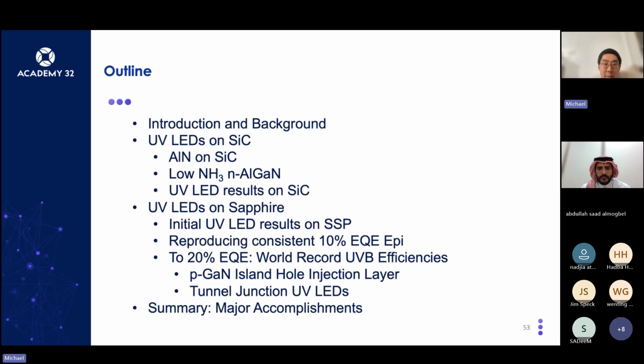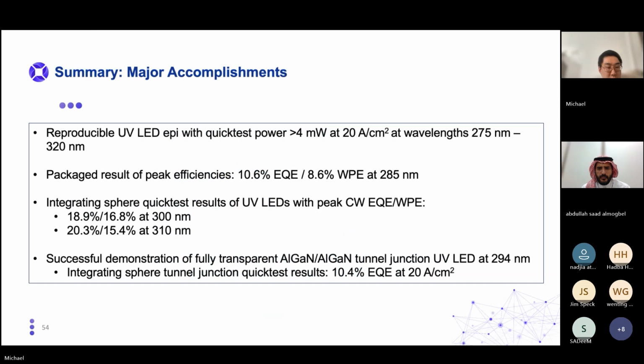So just a summary of my major accomplishments that I presented in this talk. What I was able to accomplish was reproducible UVLED epi with quick test power greater than 4 milliwatts at 20 amps per centimeter squared at wavelengths between 275 all the way to 320 nanometers in MOCVD. And the results of peak package efficiency of 10.6% EQE and 8.6% wall plug at 285. This was old results from 2023.